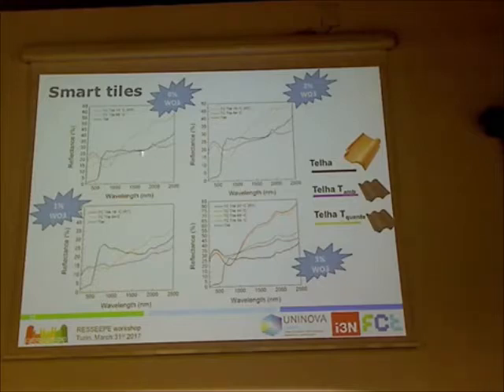Here is the comparison of the uncoated tile, the black line, with the coated tile's reflectance at environment temperature, and the coated tile at 45 degrees. This is reality—you see the big difference in reflectance. The maximum is achieved when it's doped with 3% tungsten oxide, going from the uncoated tile to the coated tile above the critical temperature. You can get something like 40% in reflectance in the near infrared region. This is a really nice result.